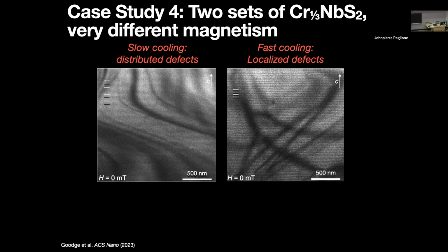We have also done some experiments, I think, which is what you're asking, where after growth, you rapidly cool down and then leave it sitting there. That seems to be probably the way to go. That seems to give you, as far as we can tell so far, and there's still more to be done, the best quality of some of these crystals.